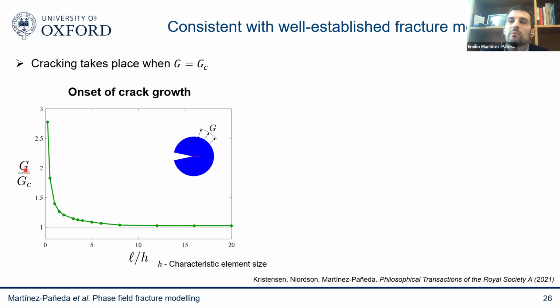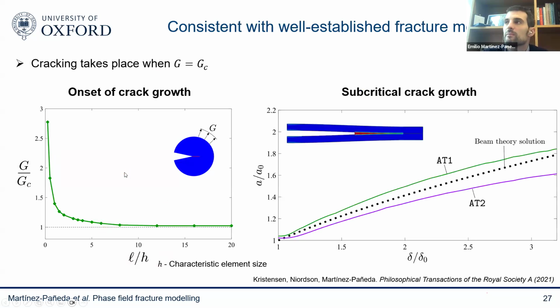And you can see this here, G versus GC at the initiation of crack growth versus the length scale divided by the element size. You can see that if you have a very coarse mesh, then you get a bad result. But as you refine your mesh, eventually you get a converged result, something that converges towards 1. So you do get the fracture initiating at the right time if your mesh is fine enough. You can see you need 6-7 elements to discretize that interface. And then you have this subcritical crack growth.